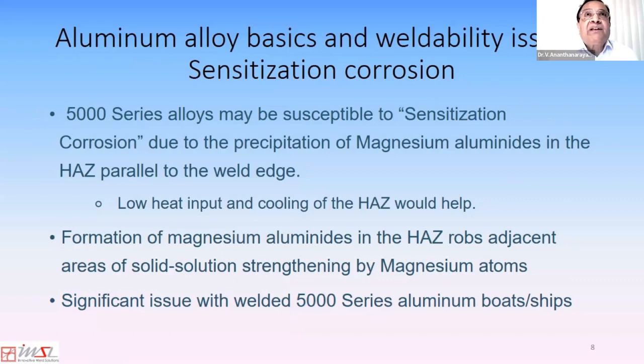This is very similar to the intergranular corrosion of stainless steels that some of you may be familiar with, where the heat affected zone of a stainless steel, if it has higher carbon contents, or if the heat input's very large, tends to become susceptible to corrosion in the heat affected zone. So this is somewhat similar, and folks use low heat input and cooling of the heat affected zone. But this is a serious problem in the welding of aluminum boats and ships that go into the sea.